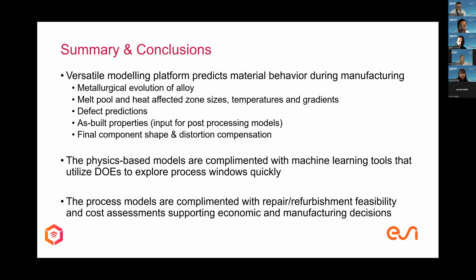Okay, so in summary, we have a versatile modeling platform with different modules which address different questions. We can look at the metallurgical evolution of the alloy. We look at the melt pool dimensions as well as the heat affected zone to make sure that it does work in tight parts, in small parts, thin parts. We are particularly interested in the actual temperatures and the gradients. We can look at defects. We can look at the as-built properties, which is also input for post-processing, like heat treatment. And we can predict the final component shape, and distortion compensation is performed if the shape is too far away from the original intent.